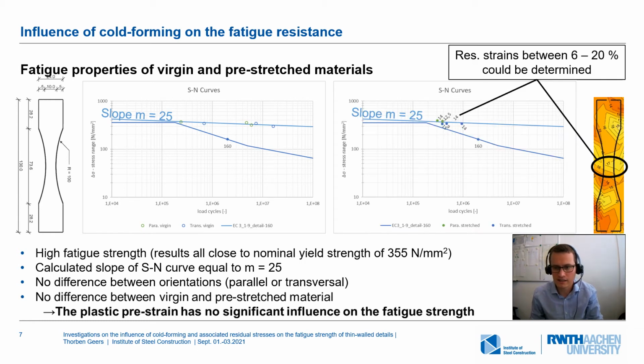On the right side are the results of the stretched samples. The value of the plastic strain is noted accordingly. However, it can be seen that there is no difference between stretched and unstretched samples. An influence of the pre-strain on the fatigue strength can therefore be excluded.